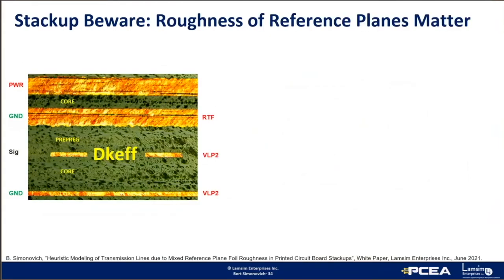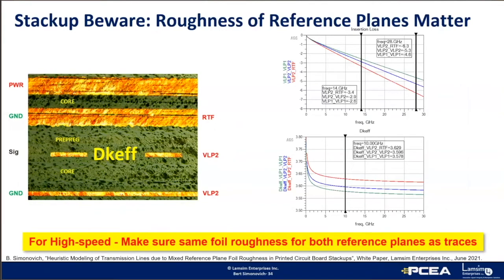And if you're worried about insertion loss, you need to consider the copper foil roughness on adjacent reference planes. Often, thin core laminate power and ground planes will specify RTF foils. But if the adjacent layer to those reference planes is a high speed layer with smooth copper, then both reference planes should have the same copper roughness as the adjacent signal layer. Failure to do so can result in a higher insertion loss for that layer and perhaps ruin your day.